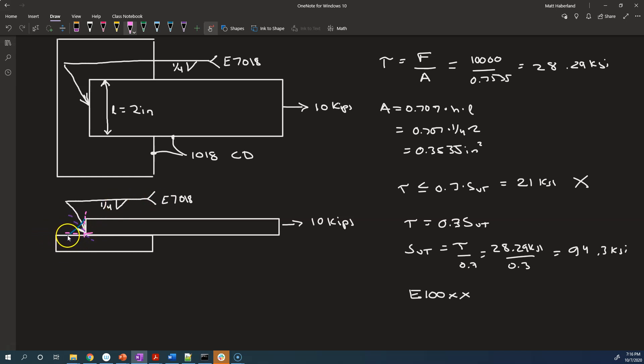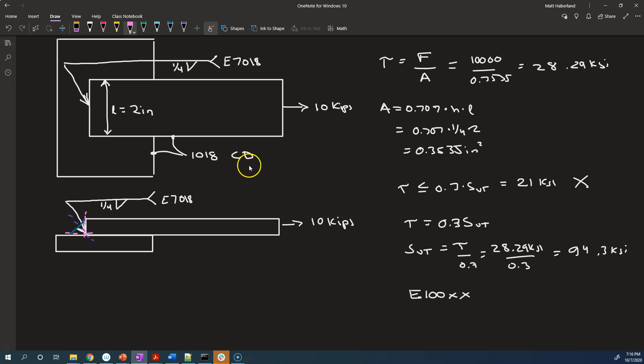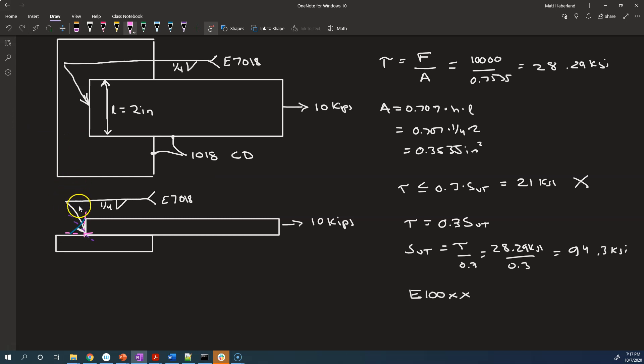Another thing is that the weld material strength — whether it's 60, 70, or 80 KSI — that's correct for that material. But if you had 1018 cold-drawn as the base metal, you might think you get to use the cold-drawn properties of the part, which are higher than the hot-rolled properties. You can't quite do that. Welding in the local region heats up that material to a point where it gets annealed, so any cold working that was done to increase yield strength — you have to assume that's no longer valid, and it could still yield at the original hot-rolled or annealed properties.